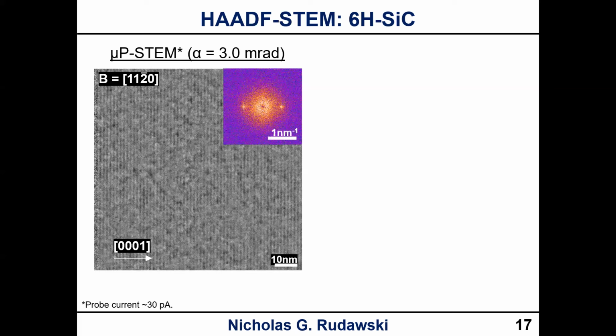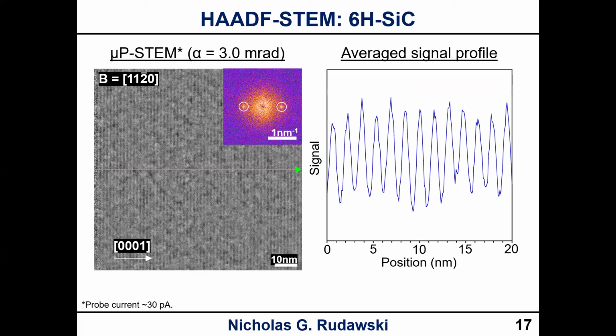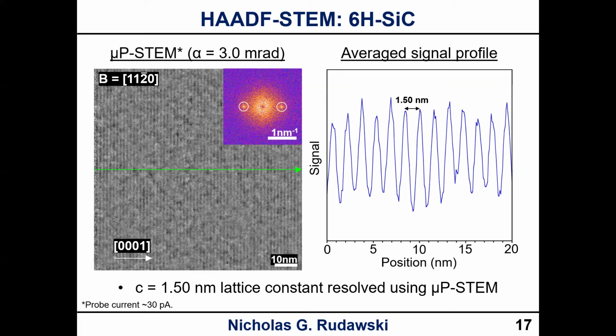If you take the FFT, you see the two spots there that correspond to that d-spacing as well. And if we look at the profile here and average it across the image from top to bottom, we can see very clearly that we have the d-spacing resolved. The peak-to-peak distance is 1.5 nanometers, which corresponds to the c lattice constant. So that is resolvable with microprobe-STEM. That's close to a nanometer, and we saw with the table before that, in principle, we should be able to get even less than this. I didn't have a good sample to test it with.